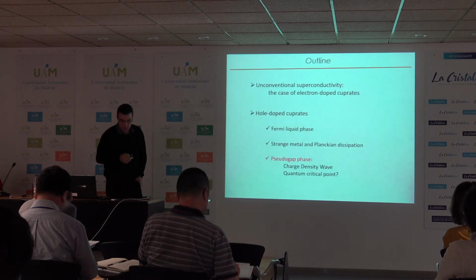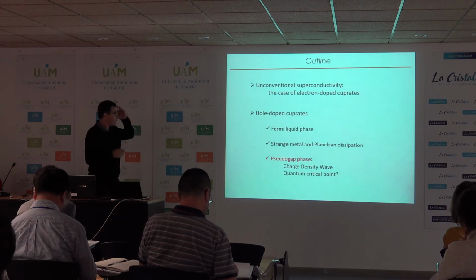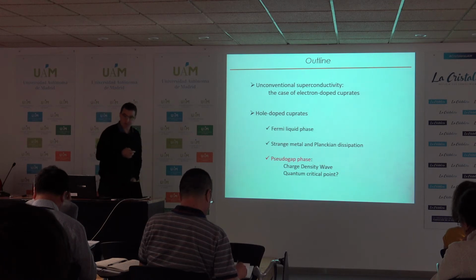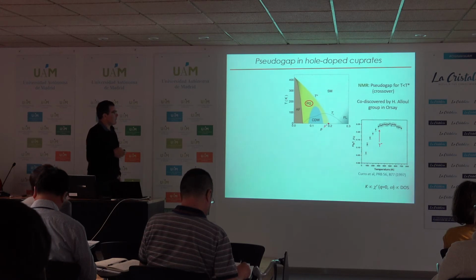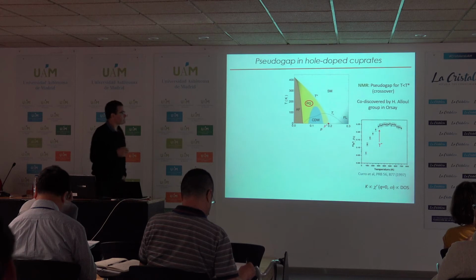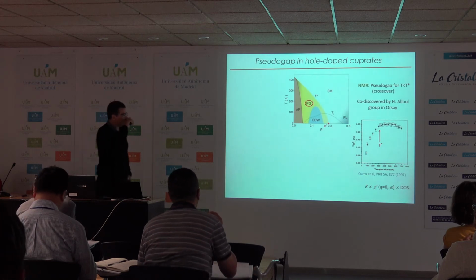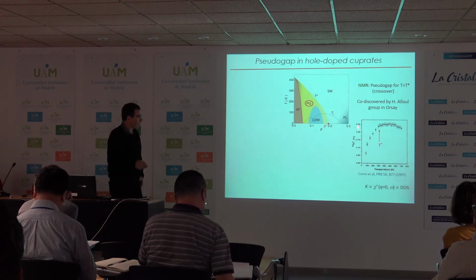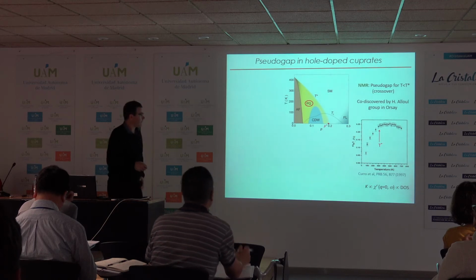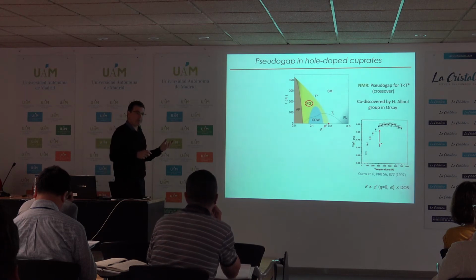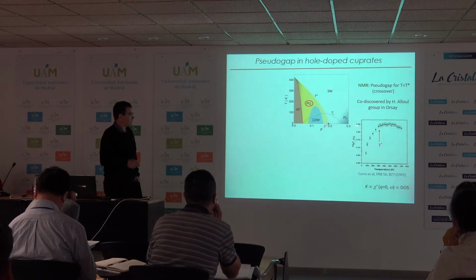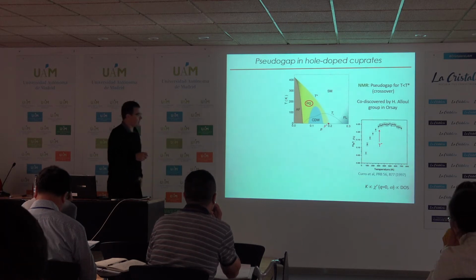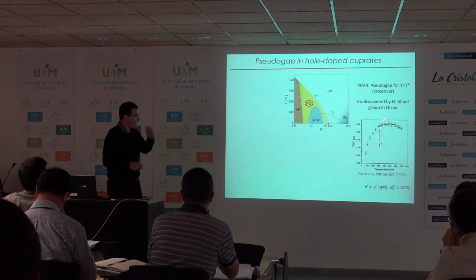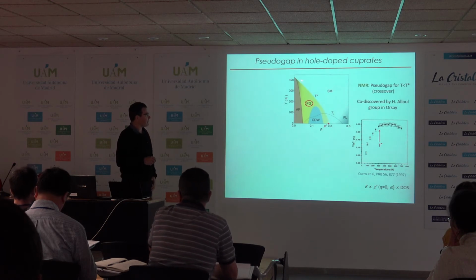So let me now go to the main topic of my talk, which is the pseudogap phase. I will mainly discuss YBCO now. Let me give a definition of the pseudogap. This phase has been discovered by NMR measurements. Here I show you the Knight shift versus temperature in the YBCO compound. The Knight shift basically measures the density of states of a metal. For a metal, of course, it should be completely flat in temperature. For a superconductor, the density of states should go down at Tc. But here, Tc is approximately here for this compound, and what you see is that the Knight shift shows a strong downturn at a temperature called T star, which is represented by this line here.